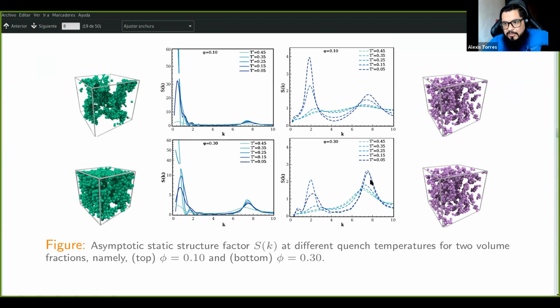The third is related with the short distance interaction between molecules, and the second peak is related with the characteristic length of these elongated clusters. I cannot assure if this first peak that we see at very low values of k is related with the size of the whole cluster, because due to the periodic boundary condition, maybe it's an artifact related to the finite size effects.